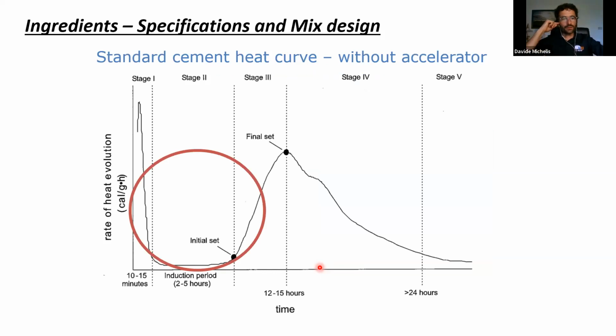This slide shows a standard cement heat curve for a standard unaccelerated mix design. You see that there is a stage 1, and I think you also see the pointer. Stage 1 is where there is a sudden increase of heat generation due to the start of the reaction of the cement. Then there is an induction period that can last 2 to 5 hours, depending on what kind of cement we are using. And then again an increase of heat generation between the initial and the final setting time. What we want to do with the accelerator is to reduce this induction period as much as possible, bringing the initial set as close as possible to the initial stage 1.